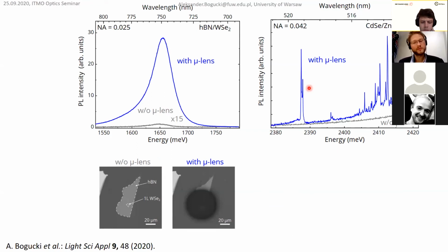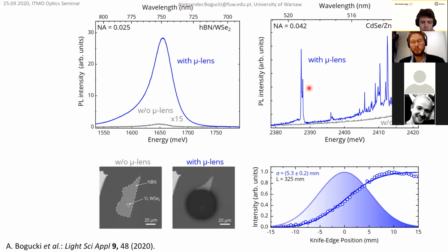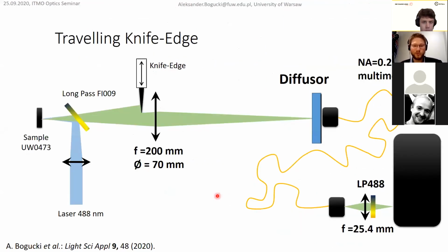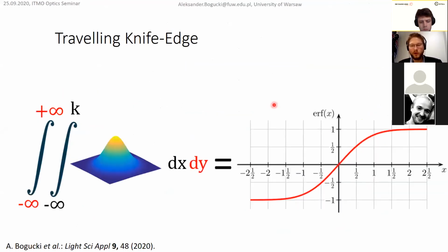Okay, so how to compare the experiment and simulation. Here is the plot of a knife-edge measurement. It means just that we put a knife edge into our beam, and we are moving it into the beam and recording the intensity of the light. Because the beam was Gaussian shaped, we know that the integral on only one axis will result in an error function. And this is exactly what we observe here. So this is the measured error function and the corresponding Gaussian distribution of our beam. And from that, we can determine the parameters.